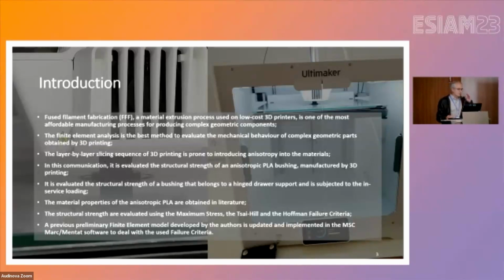The material properties of the anisotropic PLA are obtained in the literature. The structural strength is evaluated using the maximum stress, the Tsai-Hill and the Hoffman criteria. A previous preliminary finite element model developed by the authors is updated and implemented in Marc software to deal with the used failure criteria.